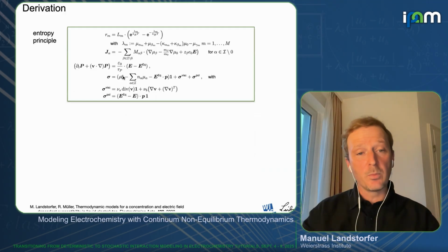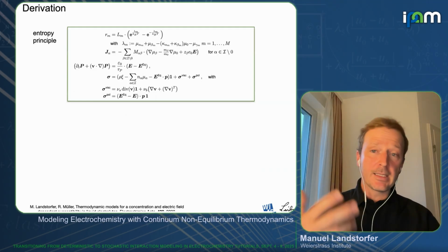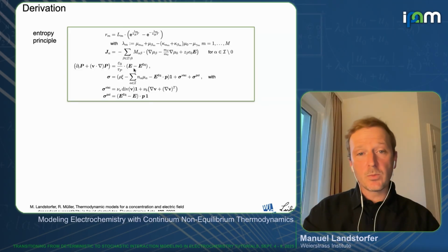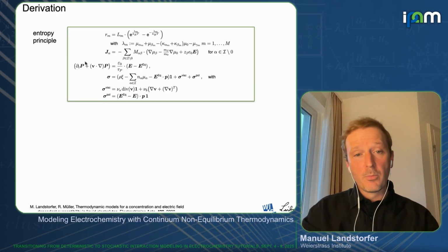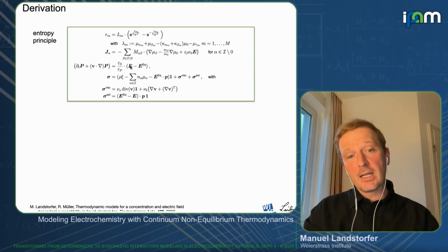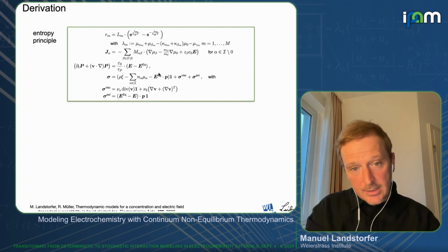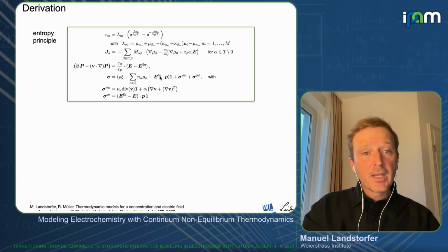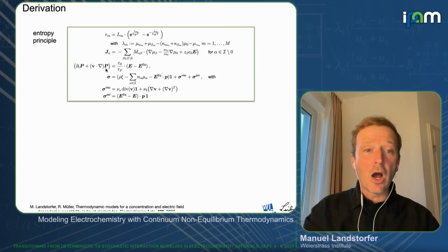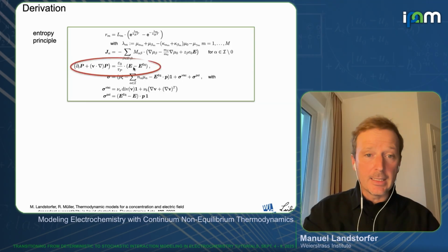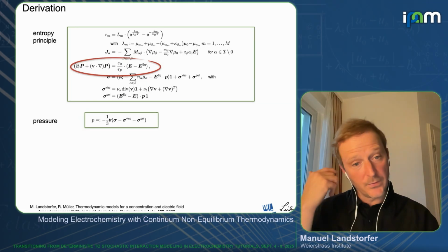So what you do is derive, let's say, the local second law of thermodynamics, where you account for the fact that polarization is a time-dependent quantity, and you can then really see that whenever the electric field is not equal to the equilibrium field, you will have an entropy production. This is basically written here. And this tells you how you have to choose the polarization vector with respect to E. And in essence, this is what we exploit further on.